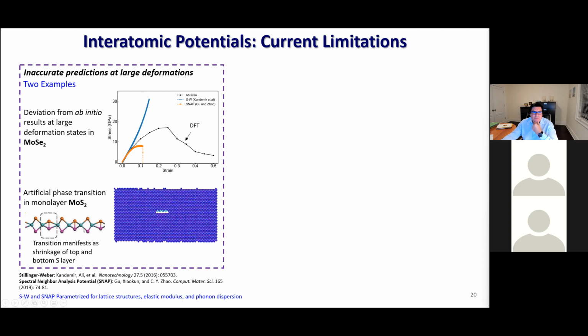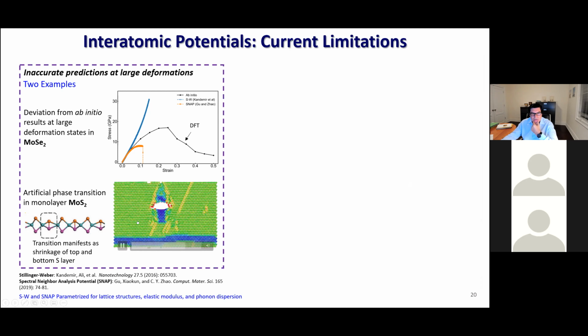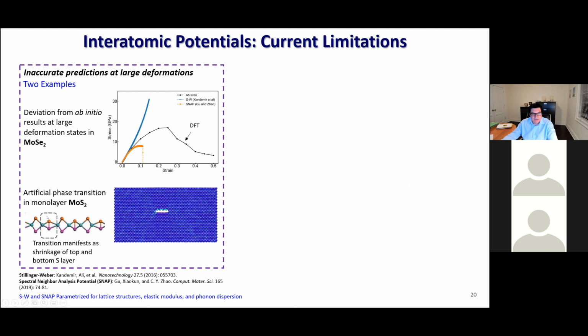The other thing that happened is this was for molybdenum diselenide. For molybdenum disulfide, another material that there is a lot of interest in the community, we ran these fracture tests with a potential reported in the literature. And I will show you that this predicts this transition, which is not supported by DFT, in this sense, that the transformation is these two sulfur atoms come close to each other. And those are the regions that you saw that initiated at the crack tip and propagated.